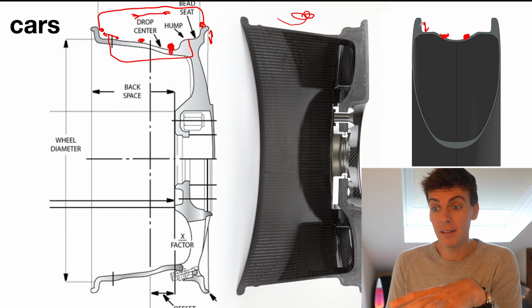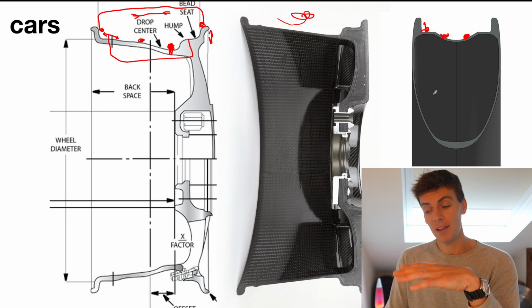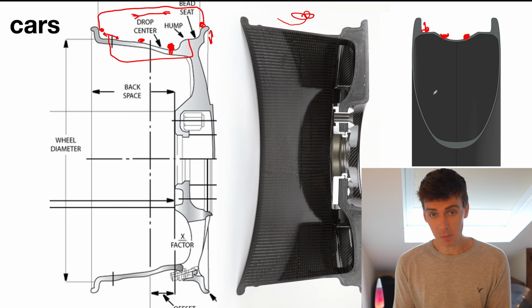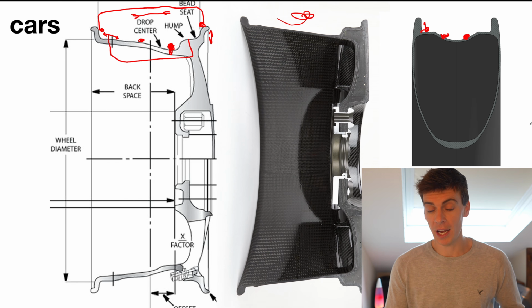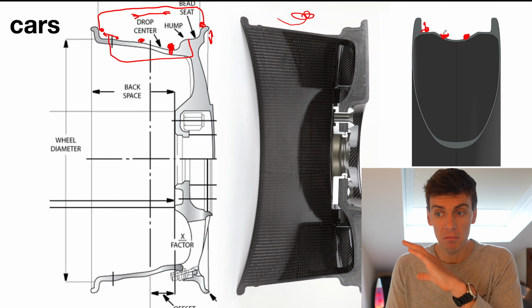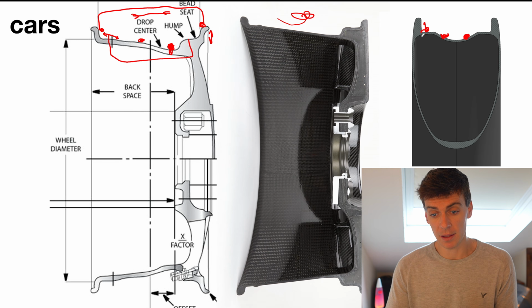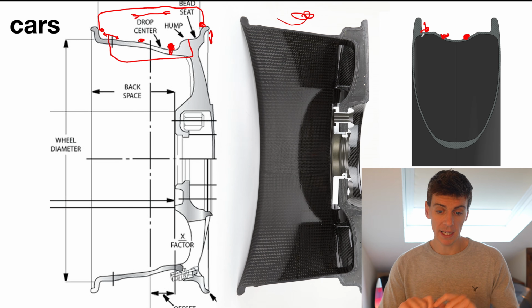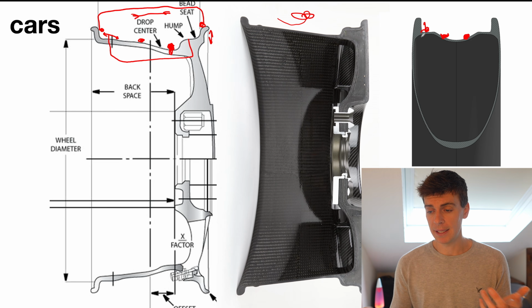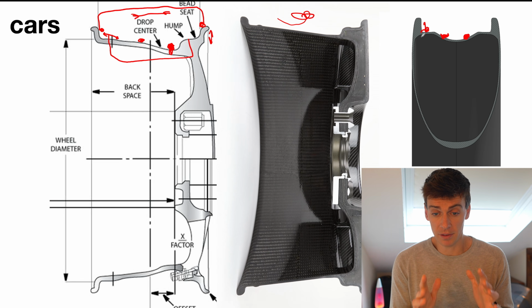So if we want to do it by hand, and if we want really lightweight, 250 gram tyres with folding beads, this doesn't work. If we had non-folding steel beaded tyres, let me think, like really cheap bike tyres that had really set diameter to plus or minus 1 millimeter, because this bead seat diameter is like 622 or 621.5, and that could be controlled to plus or minus 1 mil on the diameter, I wouldn't have any problems running hookless, tubeless. But our industry can't provide that because of the weight weenie thing. We want folding Kevlar beads, we want easy to mount, blow up with a CO2, and yeah, it just doesn't work. It's not possible to achieve that with a really floppy, skinny sidewall.